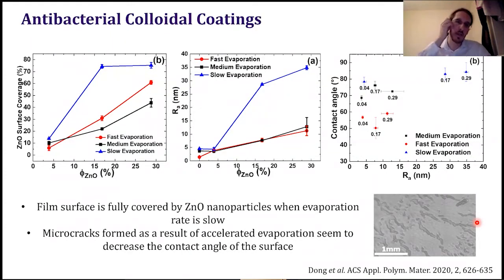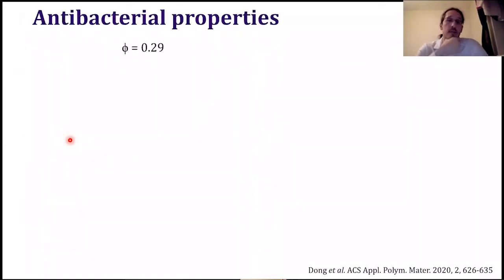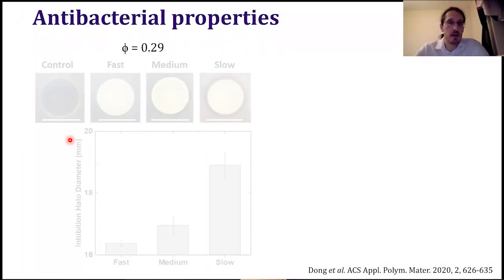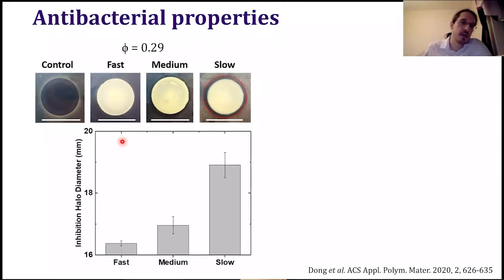So the next thing we did is, okay, we have these structures of zinc oxide at the top, but do they kill bacteria? So we did some testing using E. coli. And what you can see here is pictures of an agar plate which has E. coli incubated in it. Basically, this round thing is our antibacterial film on a glass slide. We put it upside down on this agar plate, and then we incubate E. coli.